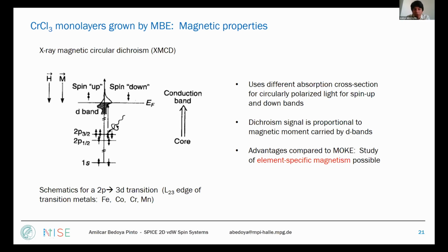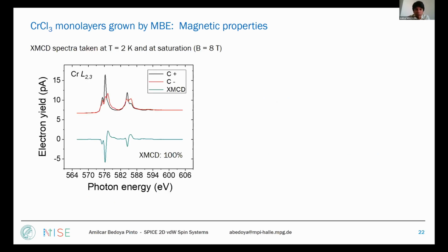So you have to do it for left and right circularly polarized light, and the difference would be proportional to the magnetization. The advantage compared to the magneto-optical Kerr effect, called MOKE, is that here you have the possibility to study the magnetism element-specific. That means you can, for example, investigate what is the local magnetic moment on chromium and on chlorine separately. So that's also very important for the magnetic characterization of those monolayer materials.